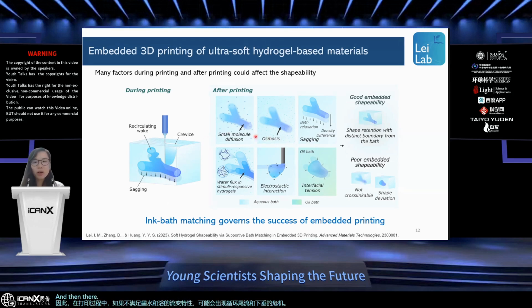And then there also could be molecular diffusion. Small molecules could diffuse between the ink and the bath during printing and after printing, and this will sacrifice the print resolution. And osmosis, there could be water diffusion into the ink phase, and electrostatic interactions as well as interfacial tension. So these factors will affect the embedded shapeability, and this will cause poor embedded shapeability.